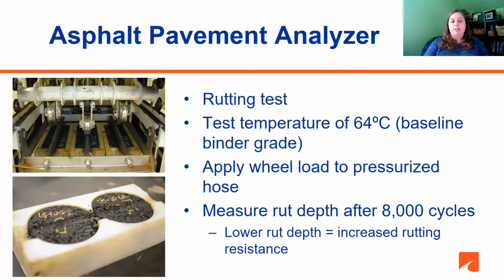For the asphalt pavement analyzer rutting test, you'll be making test specimens that will be tested at a test temperature of 64 degrees C based on our baseline binder grade of a PG 64-22. To perform the test, we apply a steel wheel to a pressurized hose. The wheel load is going to be 120 pounds, and the hose pressure is 120 kPa. We then measure the rut depth after 8,000 cycles. Lower rut depth results in increasing rutting resistance.